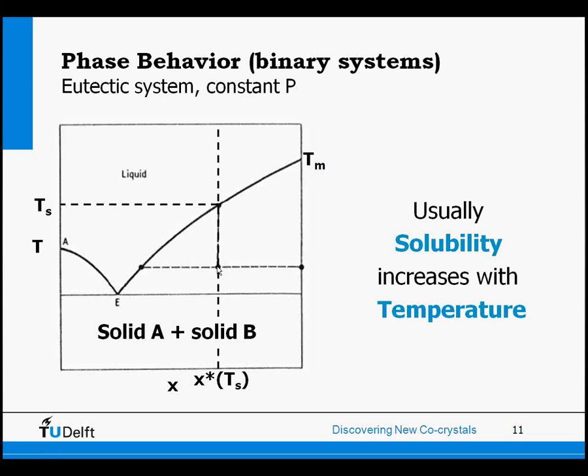And well, you want to know the solubility of these crystals, so if you then slowly heat them up and record the temperature, there will be a temperature where the solution becomes a clear solution, and that is the saturation temperature if you measure accurately enough. You know the composition of that saturation temperature, so you know a solubility point in your solubility graph. Here you see that usually solubility increases with temperature.